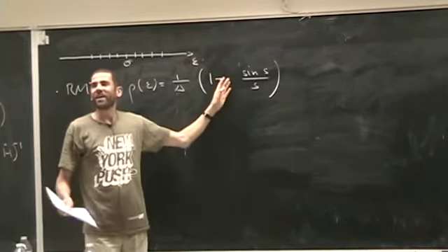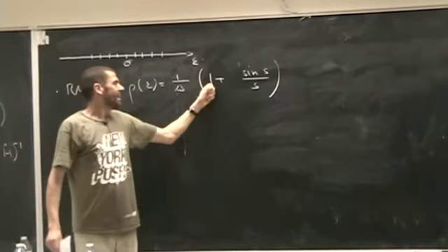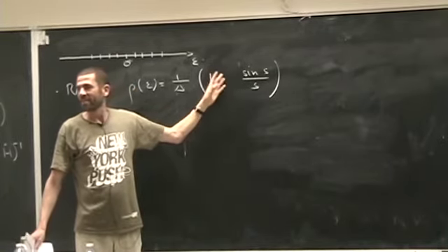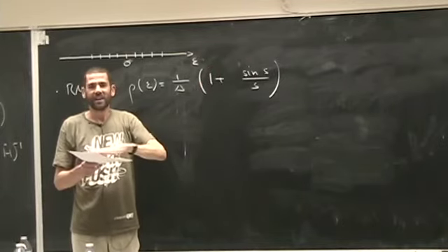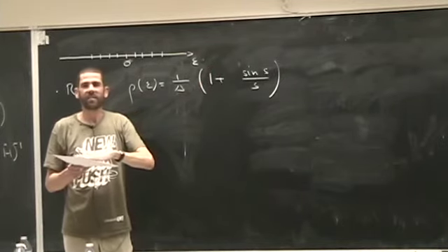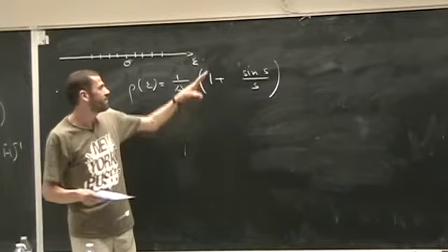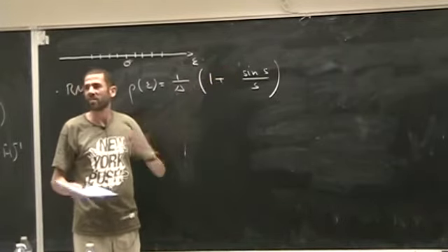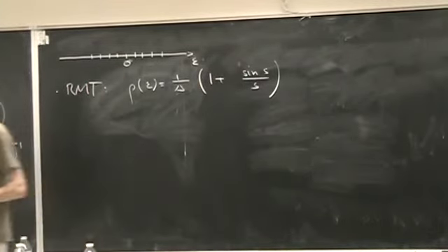This plus, by the way, just anecdotally, is responsible for the fact that in current Majorana experiments it is so hard to discriminate between real Majoranas at the band center and disorder effects. Levels really want to go down to 0 energy, and it's very hard to distinguish them from real Majorana states. Such a remark.